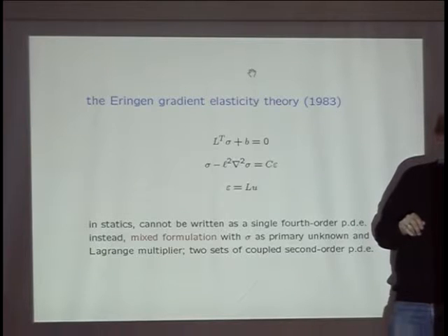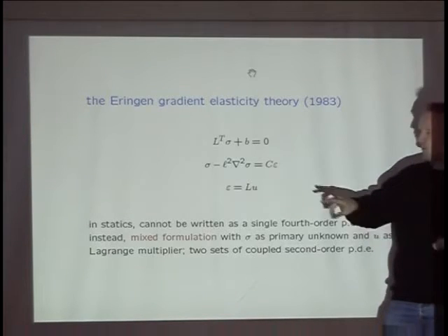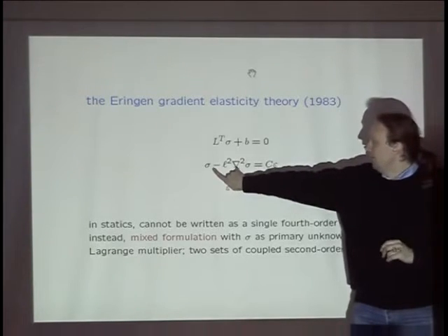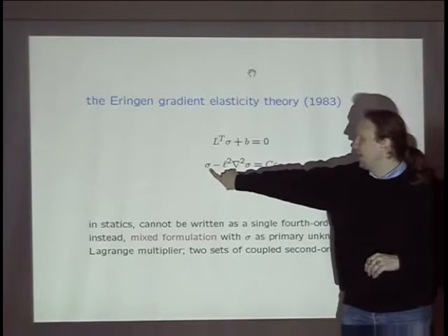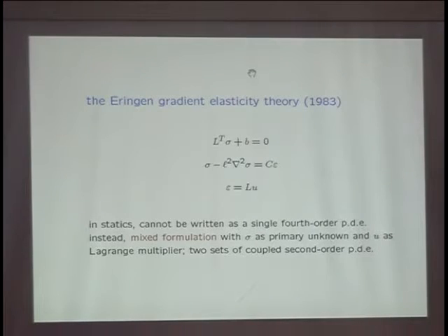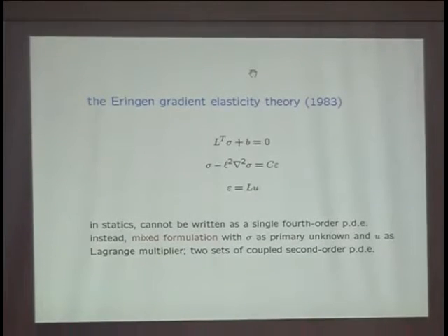To give another answer to what you started to say: this is now in differential format, but it is equivalent to taking a weighted volume average of the stress. I never quite know physically whether you want a volume average or an area average, but if you're thinking of the formation of a crack, you could argue a crack is an area feature, and therefore an area average is perhaps more appropriate.